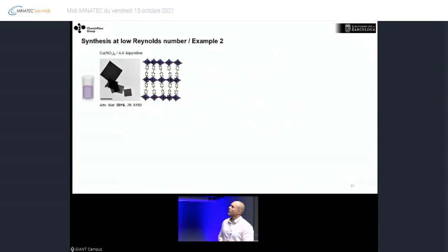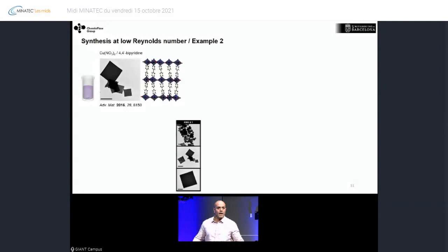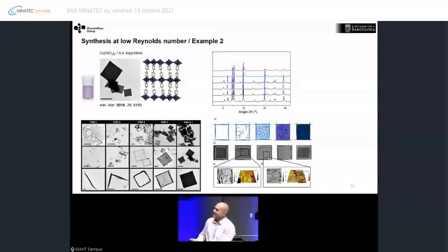So this is another example. This is another porous coordination polymer. So in that case, if we do the reaction in bulk, we have these square plate crystals. So the idea here was, okay, what will happen if, again, we do the synthesis changing the flow rate ratio? So what you see is that at really low flow rate ratios, we have the same kind of crystals. But now, if we start to increase the flow rate ratio, we go through a series of intermediate states that have the same diffraction pattern, but that you cannot obtain in bulk synthesis, even when using surfactants.